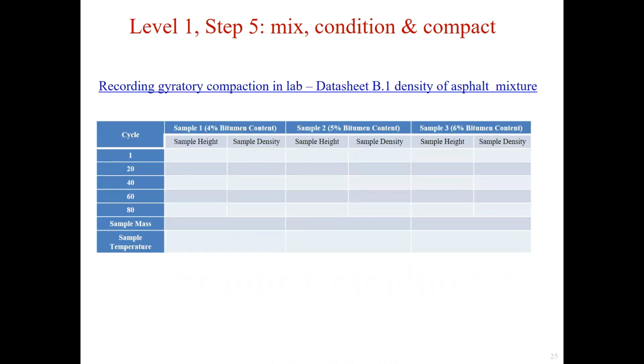This is the data sheet for gyratory compaction tests. This enables a selection of different compaction levels to match service conditions, and simulation of long-term heavy traffic by compaction to refusal density. The refusal density is also the final density of the sample.